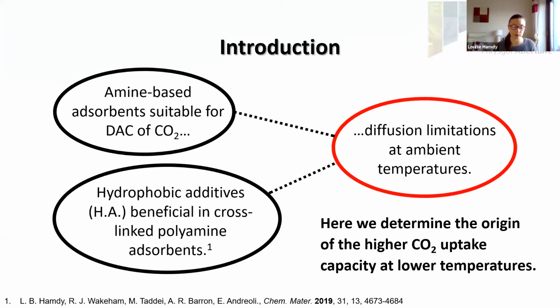However, many polyamine-based adsorbents suffer diffusion limitations. They lack the ability of CO2 to enter the pores of the materials and come into contact with the amines and thus be able to adsorb the CO2. We have found, looking at unsupported cross-linked polyamine adsorbents, that introducing a hydrophobic additive into the material is beneficial for the CO2 uptake. So in this research, we've produced a new adsorbent, and we've determined the actual origin of this higher CO2 uptake capacity at lower temperatures.